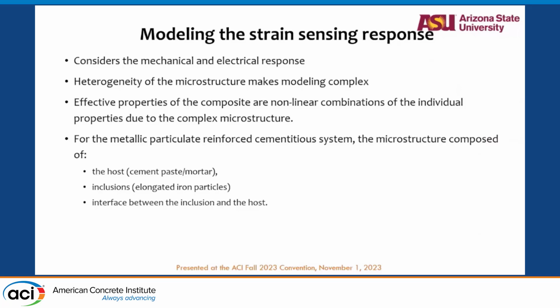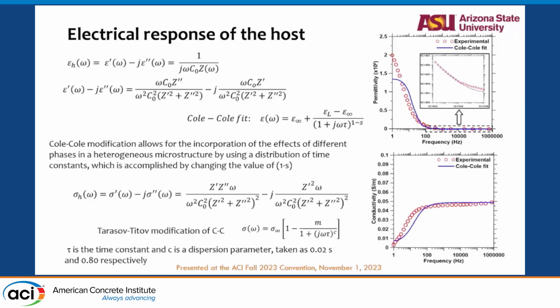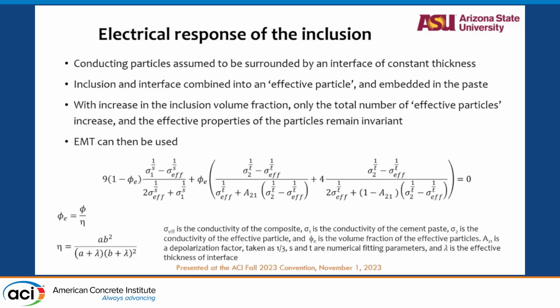So again, after the experimental result, we wanted to model it to see the replication of the results on a model. The consideration was that the microstructure is heterogeneous, and this makes the modeling complex because now it's iron powders embedded into the concrete matrix. So how do we make that better? We had to introduce an interface, a 5 micrometer interface between the powder and the concrete, which helps transfer the properties from the concrete to the iron powder kind of linearly.